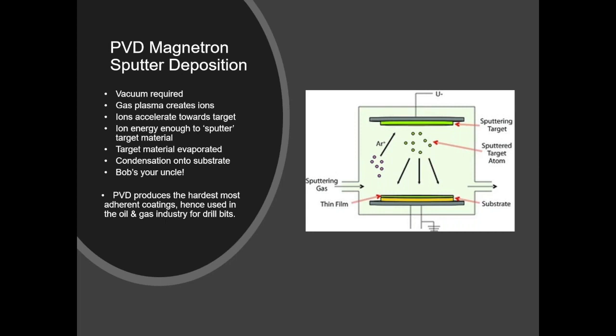Another thing about physical vapor deposition is that before we actually coat a piece, an engineering piece or a part, that piece itself is subject to a plasma cleaning process. And that means that we actually sputter material from the product, just a few atoms, but it's enough to give you an atomically clean surface. And that means when we bring in our new atoms, we can make chemical bonds at the surface. So it's not like we're making a coating that is sticking down, we are joining the atoms together, and that's the big difference with PVD.